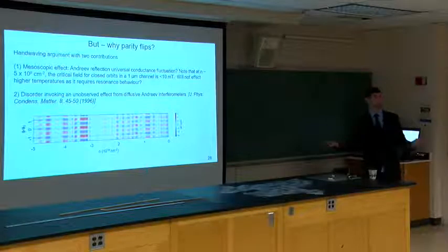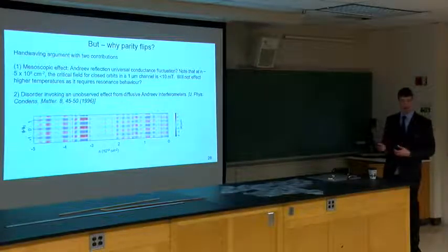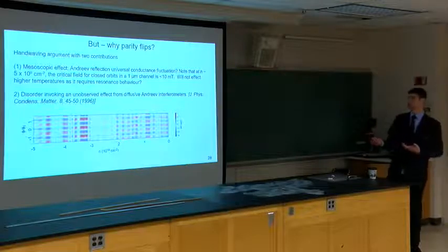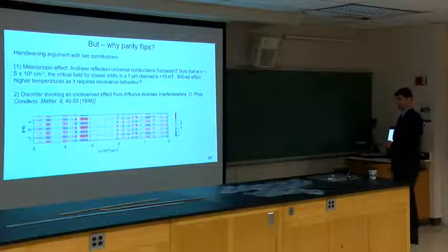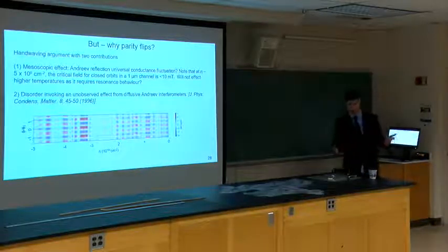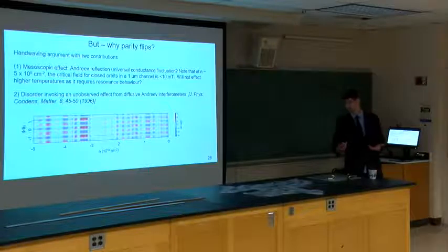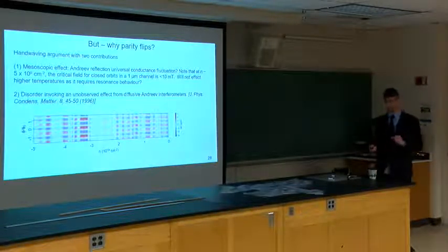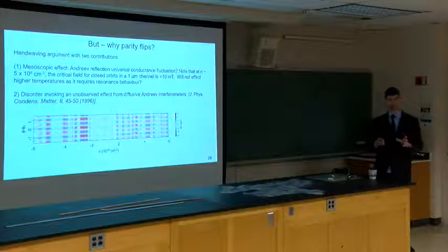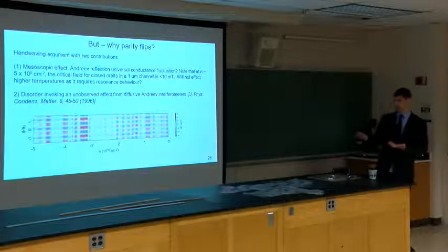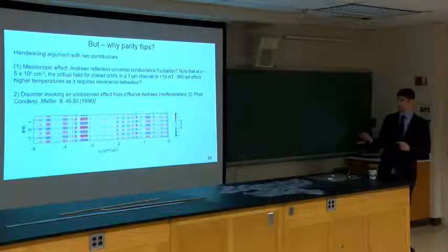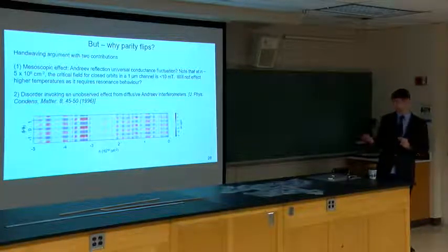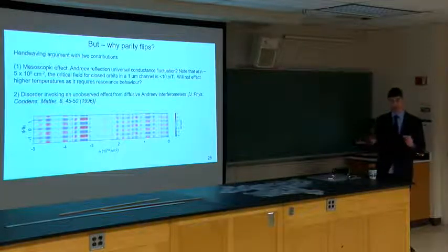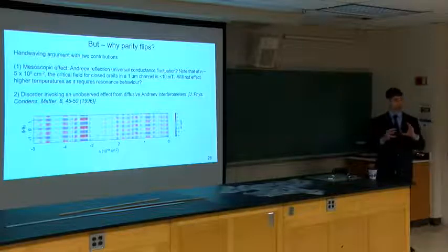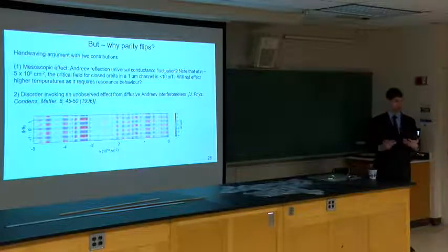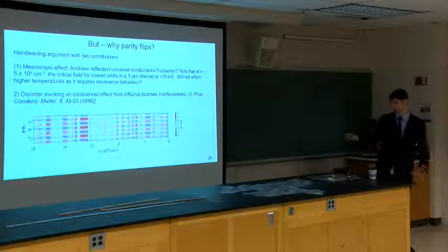This work that I'm presenting, we didn't publish this yet. We're still ironing out some of the details if it's not clear. The most likely effect is that it's a mesoscopic effect. Andreev reflection is tied together by pairs of electrons and holes that are bound by time reversal symmetry. So it's a little bit different than a universal conductance phenomenon where you just have phase coherence. It could be that just changing the density a little bit, because of the low density in the channel, the cyclotron orbits of electrons due to the Lorentz force are changing enough that we're actually seeing it interact with a different defect on the edge, or the paths suddenly retrace differently,